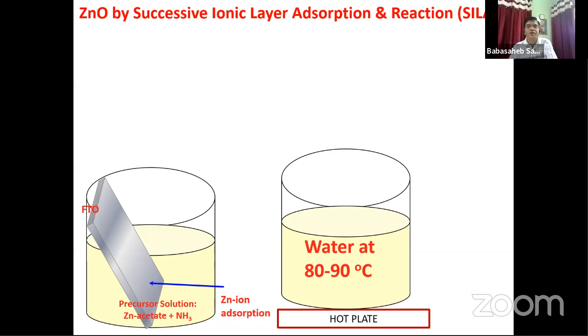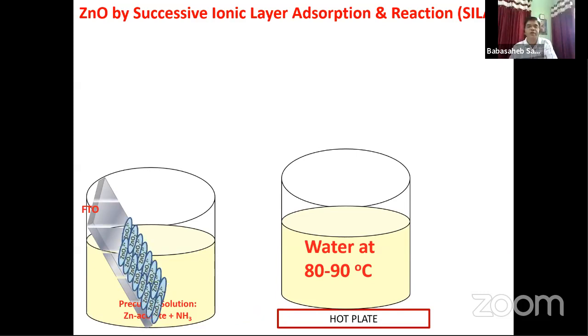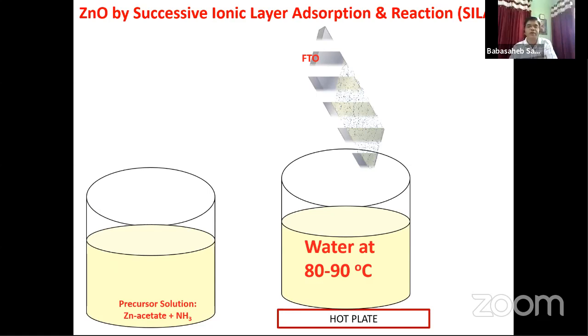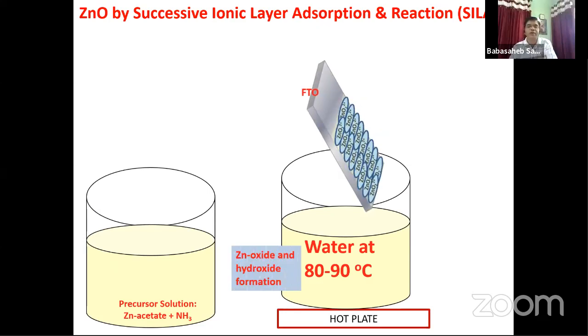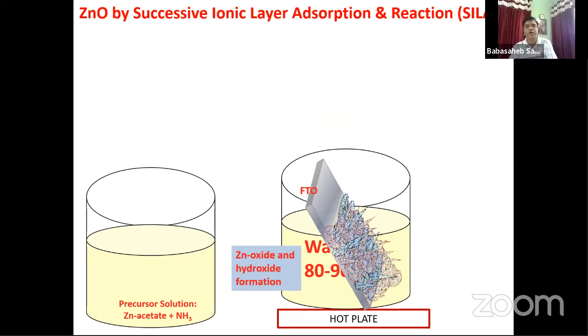Then for the anionic solution, what have we used? We have used simply water at 80 to 90 degrees Celsius, which is kept on the hot plate. It's just boiling water on the hot plate. So we have taken the substrate with the adsorbed zinc ions and dipped it inside the anionic solution, where there is a reaction between cation and anion, and there is a formation of zinc oxide and hydroxide on the FTO coated glass substrate.